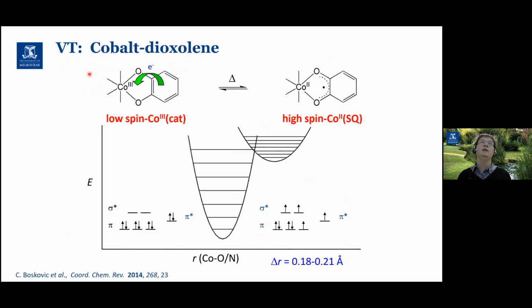In those complexes, just focusing on the thermal transition, at low temperature you have a cobalt-3 form coordinated to a catechol version of the ligand. When you heat it, you get electron transfer from the catechol to the cobalt-3, reducing it down to cobalt-2, and you end up with a radical semiquinonate ligand. Now, a really important thing accompanies that electron transfer, and that is that you see a spin transition from low spin cobalt-3 to high spin cobalt-2. So here we have the relevant potential energy wells and also the electronic distribution.